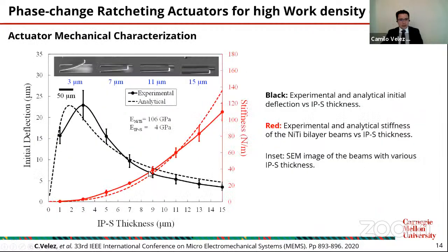We generated some models for this, using analytical models and also COMSOL simulations. At the beginning, we tried one single cantilever without passing current, heating it externally. We corroborated the implication of having a different thickness of the passive layer, meaning the 3D printed part, on the actuation, the initial deflection, and the stiffness of the generated material. It's very interesting because we have very good agreement between our predictions and the model. You can understand quickly that there is an optimal thickness for this 3D printed part, to get the maximum initial deflection.